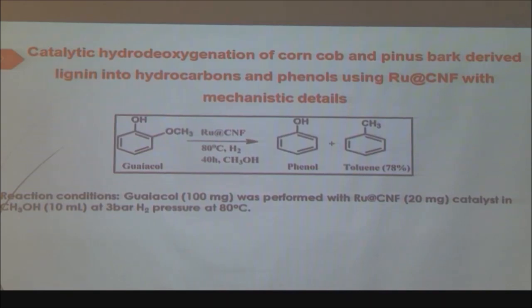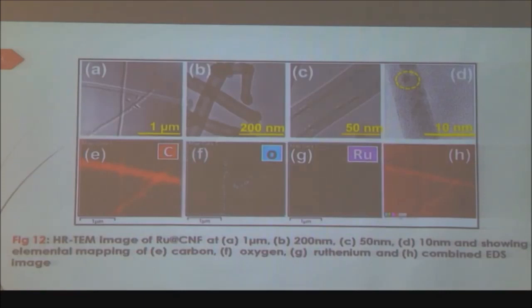We don't make a lot of catalyst. So what we did, again we characterized what type of catalyst it is. There are metal particles, and the ruthenium metal is also present on it. This is the HRTEM analysis that shows the morphology, and with the elemental mapping, which is different for every element, you know which type of element is present on its surface. So we were able to see this ruthenium. It has carbon because it is mainly a carbon material. There is oxygen also, and we can also see the ruthenium, and this is a combined image.